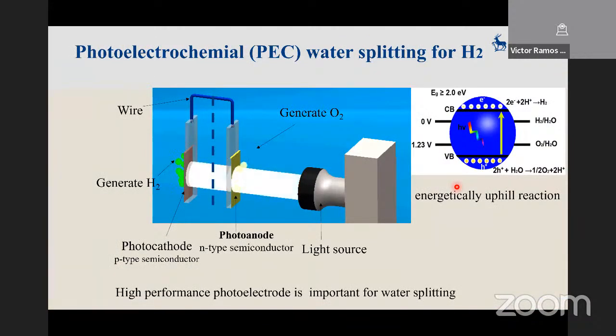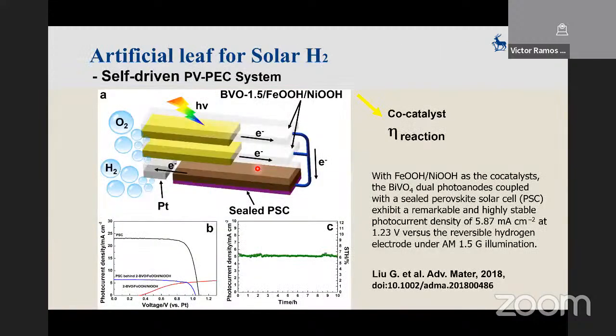And then we also did a lot of work on photoelectrochemical water splitting, because this is an energetically uphill reaction. So you need to have some electrical energy input, because of the bias, you can actually generate the hydrogen and the oxygen separately, using a membrane directly in this kind of reactor. You could also make an artificial leaf with a tandem solar cell, the photovoltaic cell based on perovskite. In this case, it's a perovskite solar cell with the artificial leaf, which is a solid state co-catalyst system using this kind of system here as a dual electrode to produce hydrogen. And then we achieved a hydrogen efficiency of 6.5%. So getting closer to the 10% efficiency.